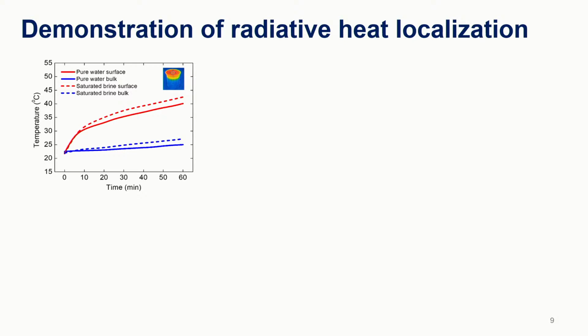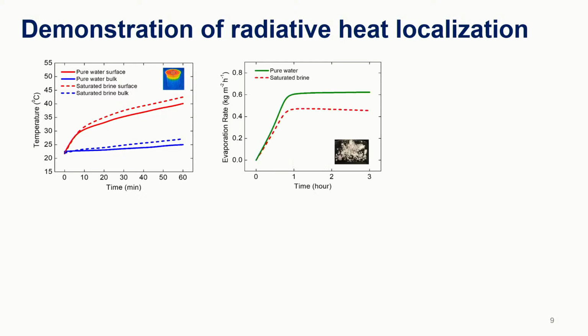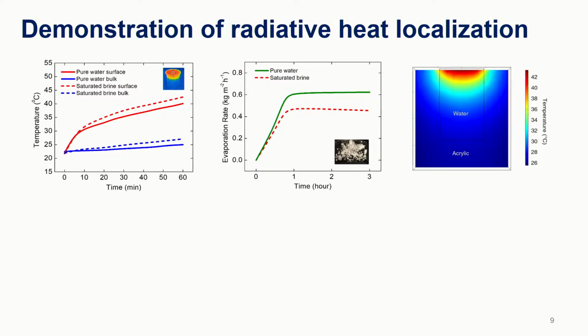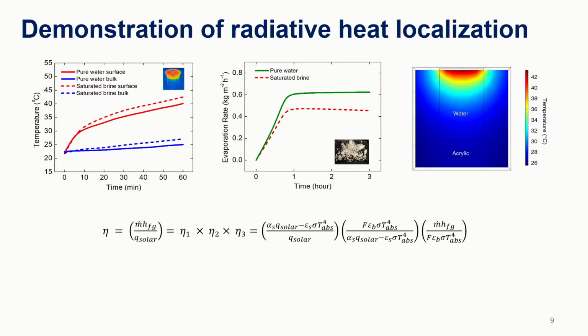And so experimentally what that looks like is if you have this beaker of water and you have your selective absorber and emitter taking in sunlight, the top surface of your water will increase in temperature. Here it increases from around 22 to a little bit over 40 degrees Celsius, while the bottom water, down here, just remains at that ambient temperature. So you're only heating the surface. And so if you let this process run for a couple of hours, you can evaporate all the liquid, and then you're left with just the salts that crystallize. And so you can completely remove all the water. And here's just some modeling we did to again show that the heat is really just localized at that surface, and the bottom of the water remains at ambient temperature.